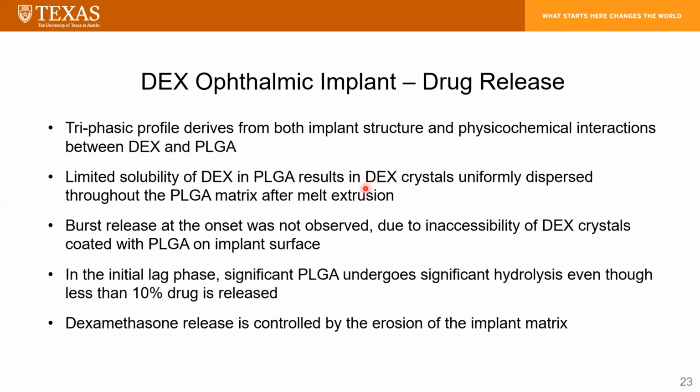There's no solubility, as I discussed earlier, and then burst release is not observed. After the initial lag phase, drug is released over about 3 to 4 weeks. And in the initial lag phase, even though there's no drug release, PLGA undergoes significant hydrolysis. In summary, dexamethasone release is controlled by the erosion of the implant matrix.